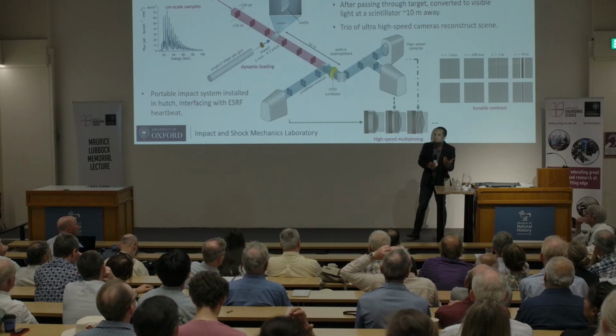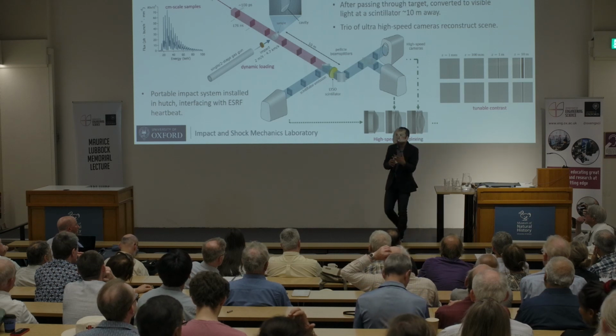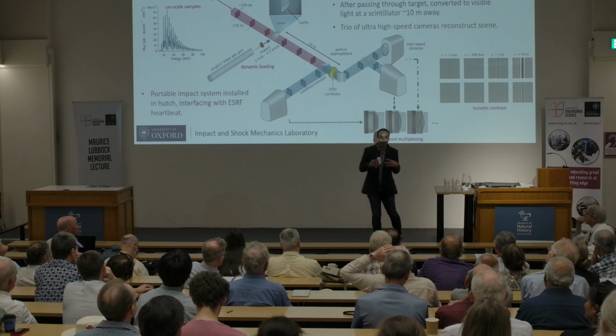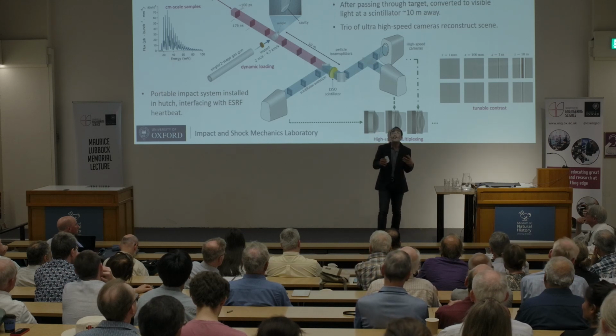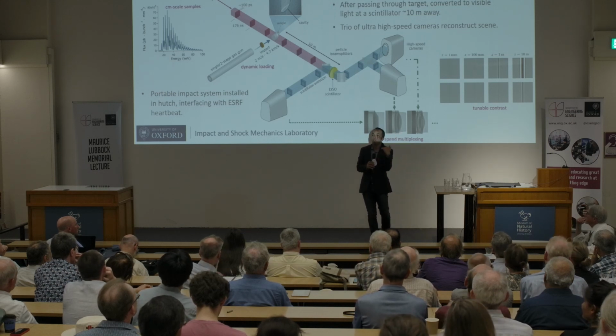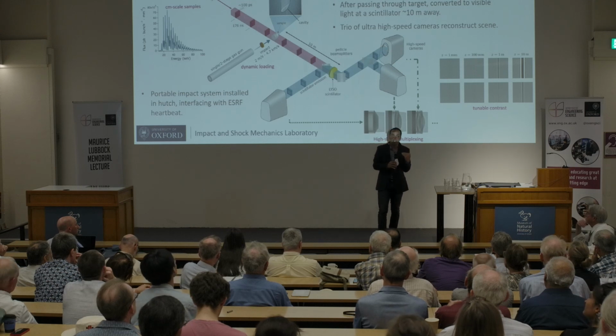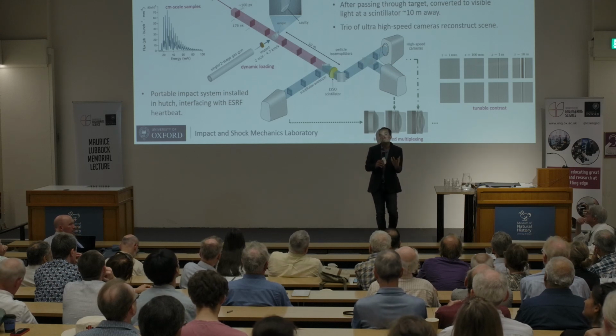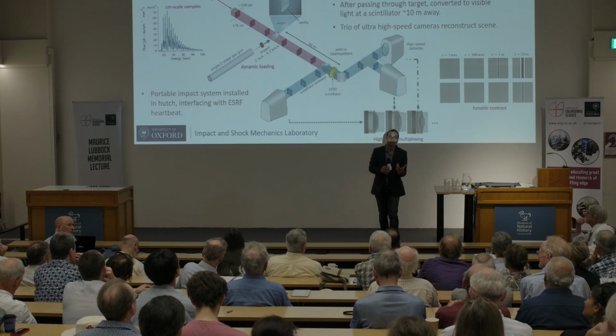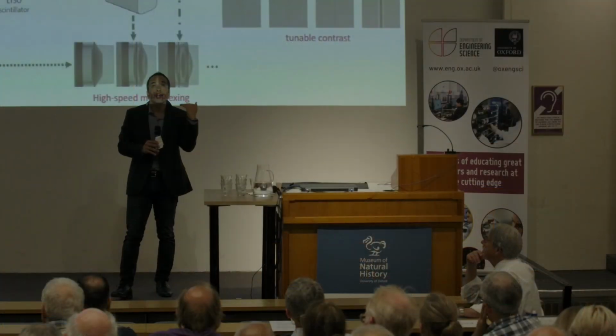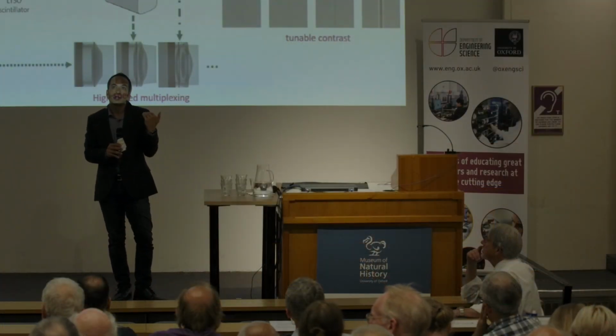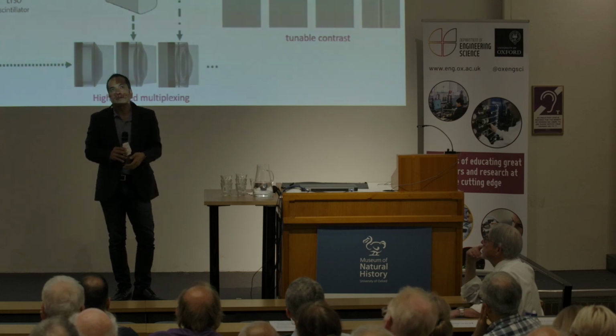Homogeneous nucleation takes advantage of the fact that in any pure solid, you still have a statistical misarrangement of those atoms. And so if the threshold is high enough, you can actually produce a defect where there was nothing before. So that's what that is. That is a higher energy pathway for producing damage within a material. And it really requires those extremely high strain rates in order to do that.